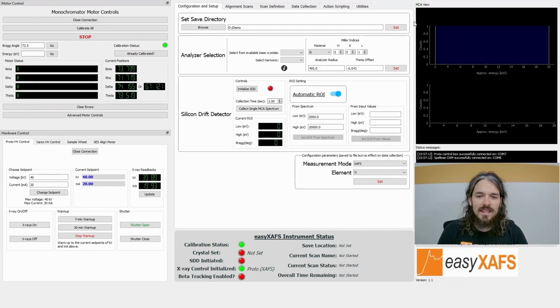First we'll set the save directory. Next we'll select the crystal analyzer that we're using for the measurement. Here we're using the silicon 551 crystal analyzer to measure the nickel K edge. The analyzer radius parameter is optimized for this particular crystal and is preset to 495 millimeters. The theta offset is a calibration parameter for alignment of the beam. This is determined by a 1-minute alignment scan, and for the demo, we've already done that, so that's the value we have here.